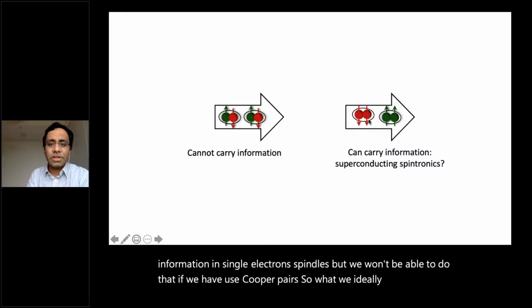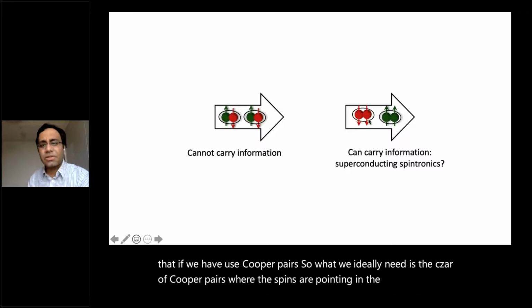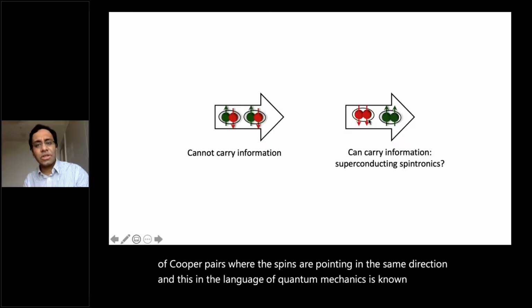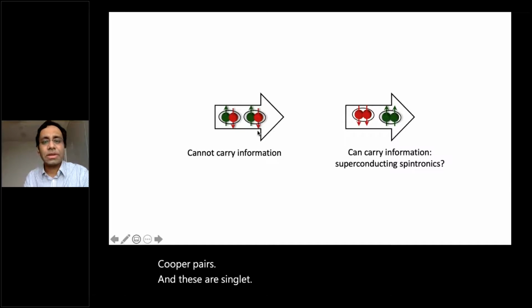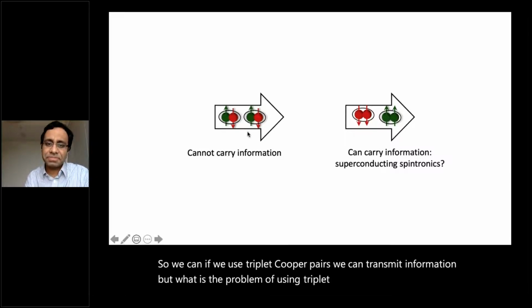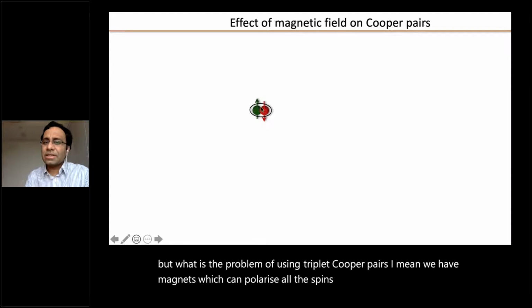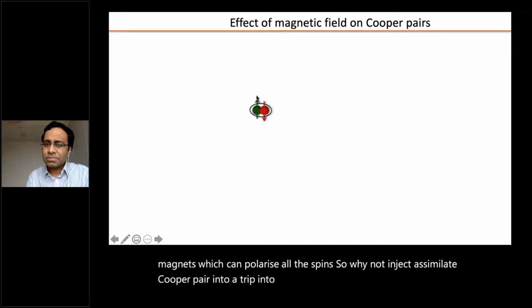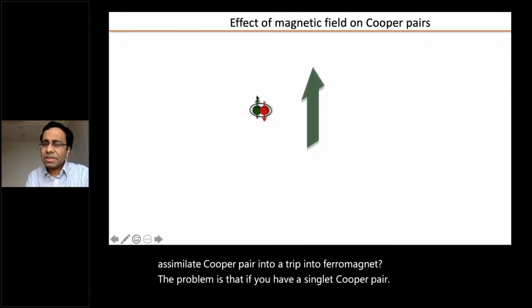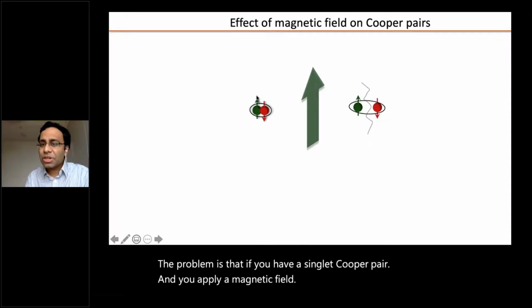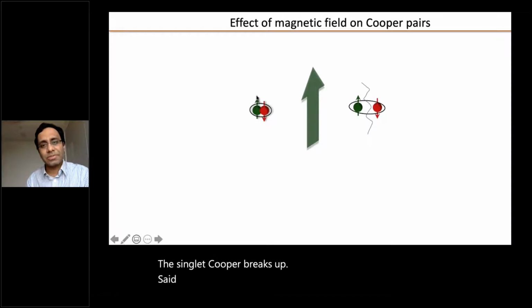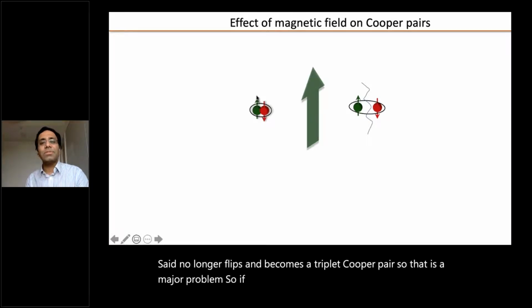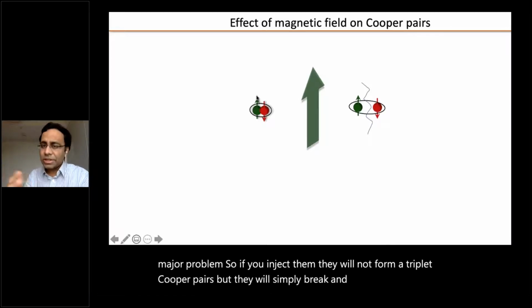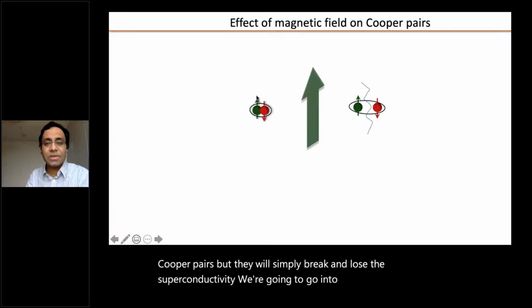But what is the problem of using triplet Cooper pairs? I mean, we have magnets which can polarize all the spins. So why not inject a singlet Cooper pair into a ferromagnet? The problem is that if you have a singlet Cooper pair and you apply a magnetic field, the singlet Cooper pair breaks up. So it no longer flips and becomes a triplet Cooper pair. That is a major problem. If you inject them, they will not form triplet Cooper pairs, but will simply break and lose the superconductivity. We are going to go into the details in the next few slides.